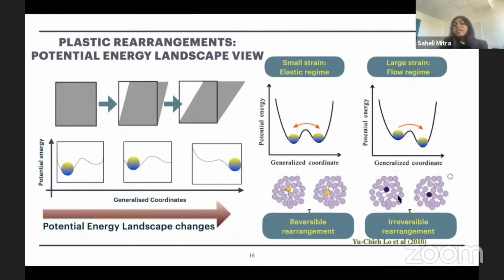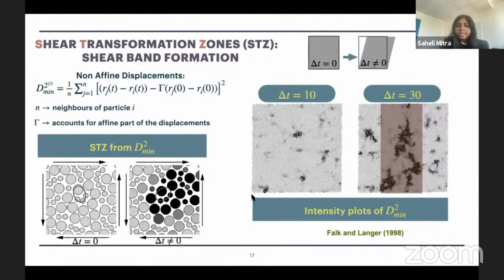Now, given a system, how can we identify the regions that are taking part in these rearrangements? We can do so by computing the non-affine displacement, which basically measures for each particle the change of local strain. Here is a zoom of a system where the particles are rearranging. At time 0, this D square minimum value is 0 for all the particles. There are no rearrangements because it's the initial configuration. Then as we go along with time, we see that there is a zone of particles in darker shade that has gone through rearrangement.